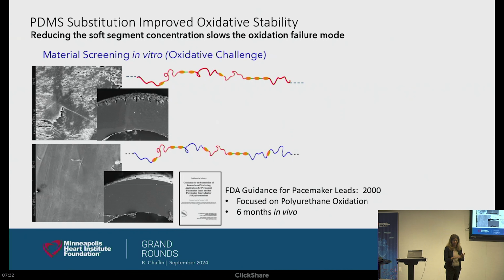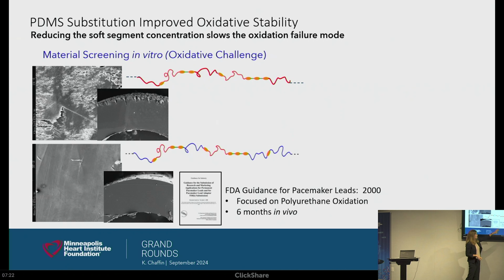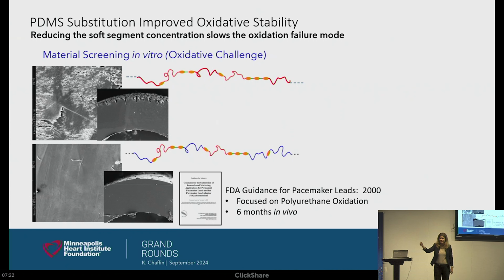Boston's being peddled this material, Medtronic's being peddled this material, St. Jude at the time is being peddled this material. And if you go back to the guidance, what the guidance says, well, we don't want MIO or ESC, so you got to do this oxidation challenge test. And if it looks good, if you don't see all these cracks, if it looks better than what your old material looked like, then you only need 6 months in vivo. It literally is the law, it's the rule. And they did it. And it looked good. We did it. Except